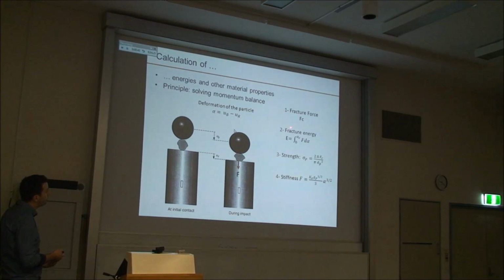By doing an integral, which is the area below the force time curve, you get the fracture energy. And this is a very important parameter. This is how much energy has been absorbed by the particle until it fractures. When it fractures, it's the fracture energy.